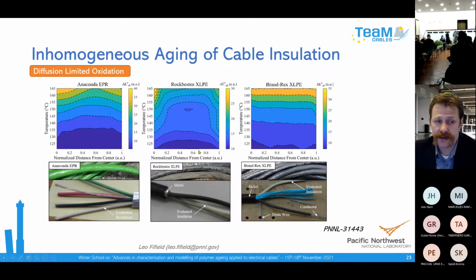Brand Rex XLPE. These are just summary plots that show, at different temperatures when we did the aging, the average results through the thickness of the material and the color change. So we saw in this example of EPR on the left, at a lower temperature of aging, it was more homogeneous through the thickness. But as we increased the temperature up to 165 degrees C during aging, we saw more of this effect of more rapid aging at the edge.